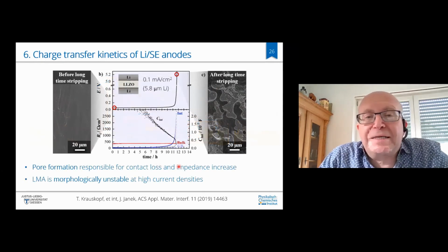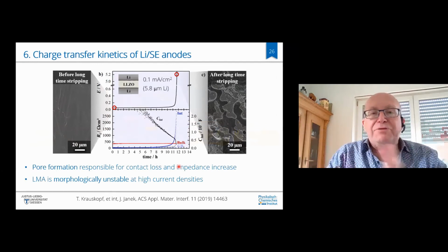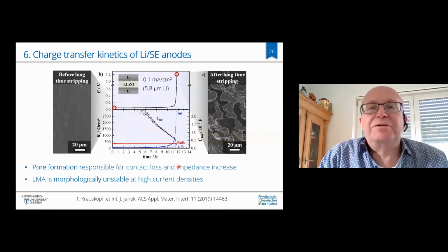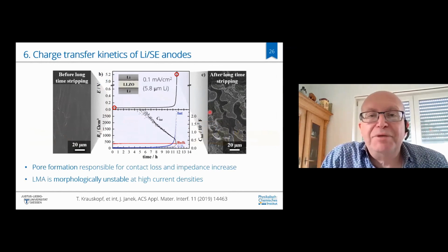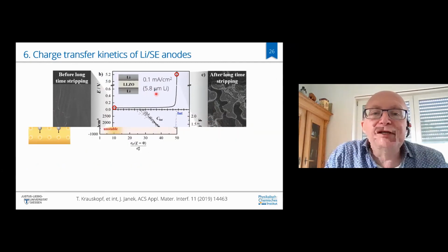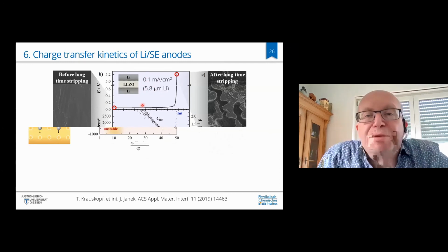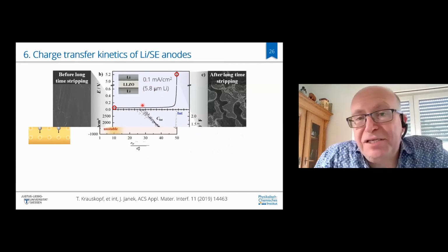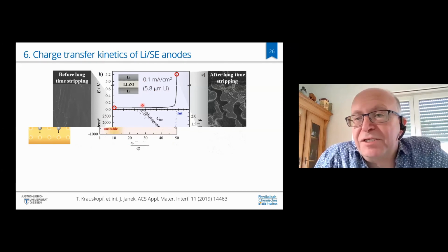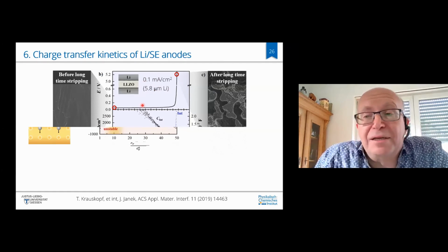Now, nevertheless, what you can show if you really prepare your electrode nicely by strong pressure, and even if you remove the pressure until sufficiently pores are being formed, I think we were able at room temperature to strip about 6 micrometer of lithium with a current density of 0.1 milliamp per square centimeter. But of course, these 0.1 milliamp per square centimeter are still, I would say, by and large, 1 to 2 orders of magnitude too small for practical applications.